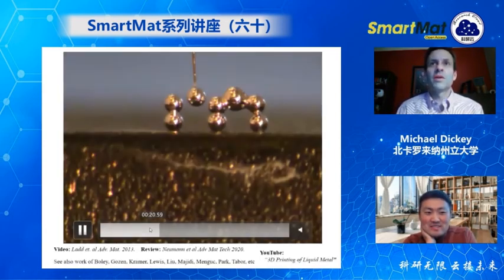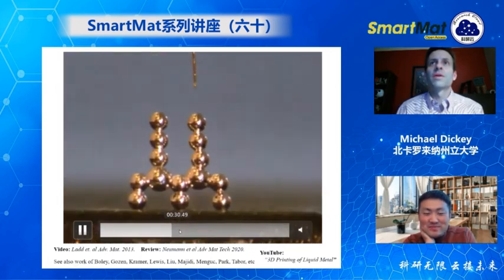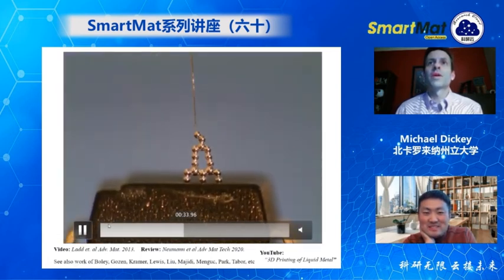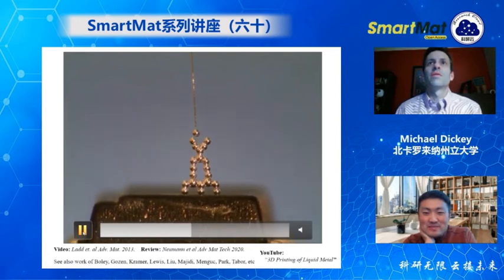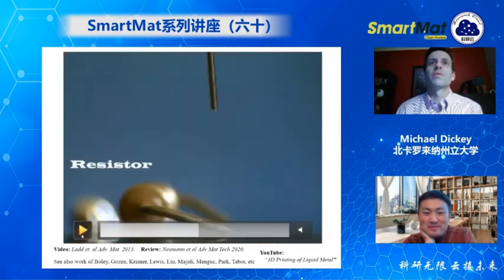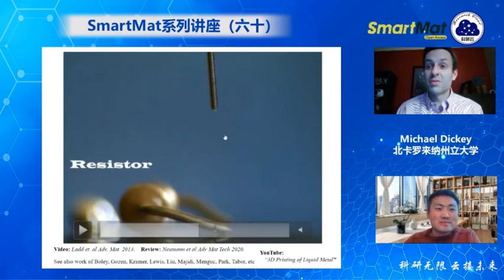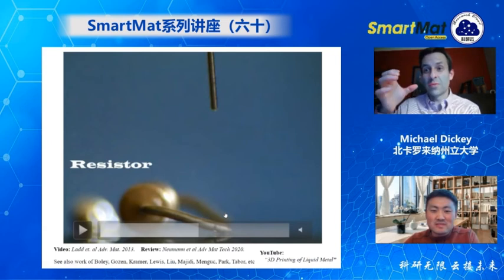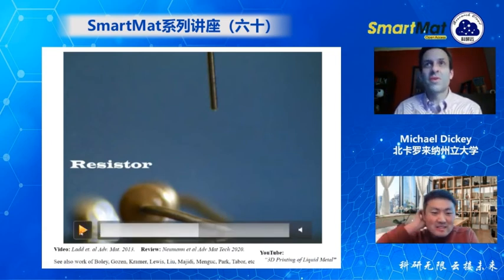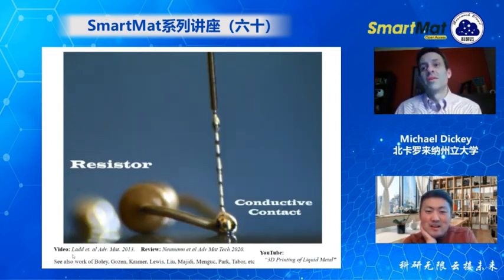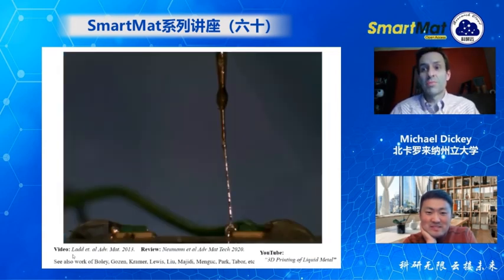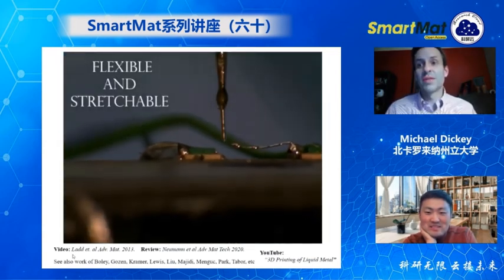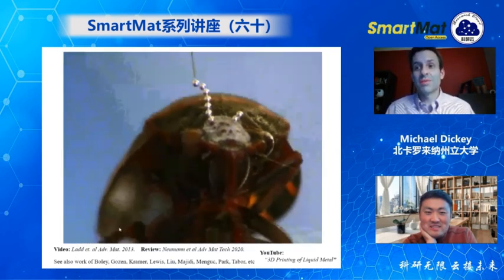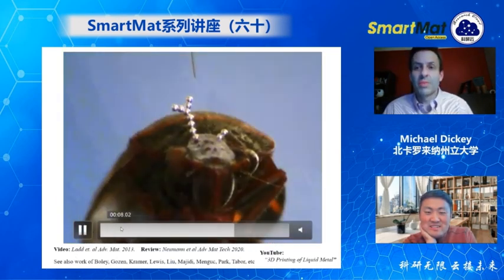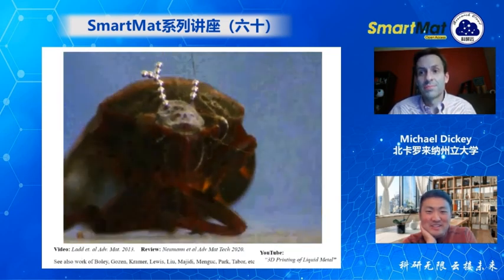But if you see right here, right after this, I'm going to pause it right here. What we're going to do is a burst of pressure. And when we do the burst of pressure, it will shoot the metal out as a cylinder and form an oxide layer. So it forms really fast. Boom. So in principle, you could print very, very fast. I don't think we've really tried to push the limits. It's probably limited by our machine and not the material.